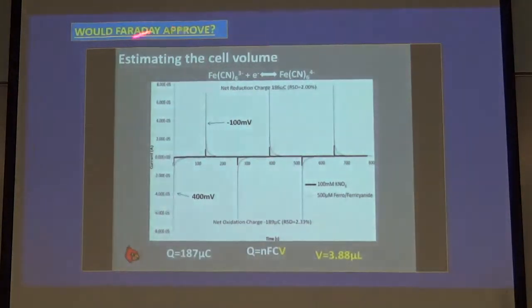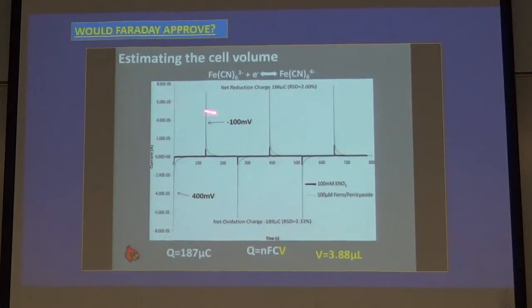Okay, in one of our first studies, we tried to choose an ideal system. The ideal electrochemical system is ferrocyanide. It just gains an electron, goes to this species, and nothing chemically of interest happens. It's chemically and electrochemically reversible. You can go back and forth all you want. So we filled our cell with ferrocyanide. We applied a positive potential to cause it to oxidize, causing this reaction to occur.